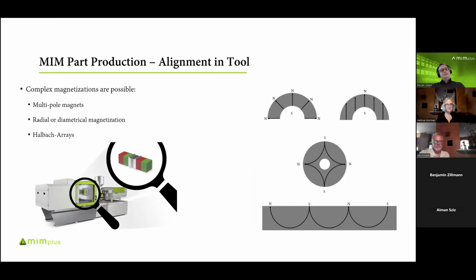And this is the complex magnetization that is also possible during injection molding. So what we can do is influence the orientation of the magnetic field lines in our cavity. With that, we can produce multipole magnets, or we can manipulate the orientation so that we can produce either radial or diametrical magnetization. And what you said before, Tim, was the Halbach arrays. That would also be possible: to introduce an alignment to get a monolithic Halbach array.